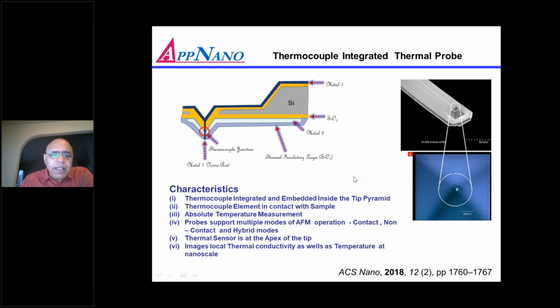So the cantilever has been designed so that it can also work in a contact or non-contact mode. The frequency for the non-contact mode is about 100 kilohertz, and the spring constant is about 10 Newton per meter. But then we also have the contact mode probes, which can be as soft as 1 Newton per meter, and their length is about 375 microns. So they are better for the contact mode. Everything has been published in this paper, if you want to get to know more about this.